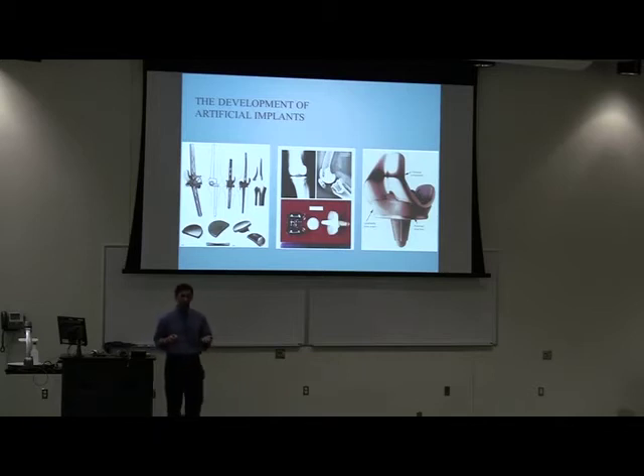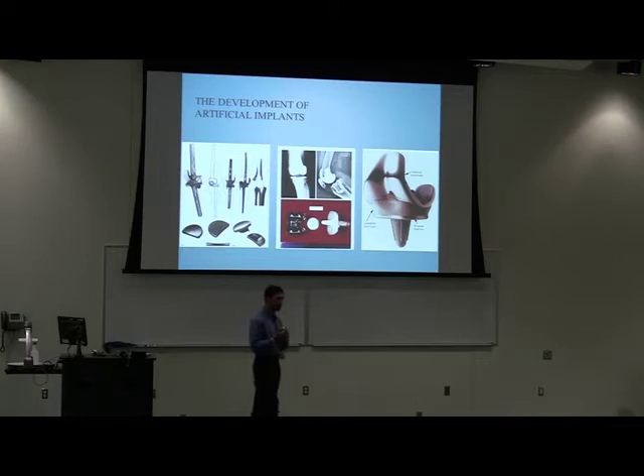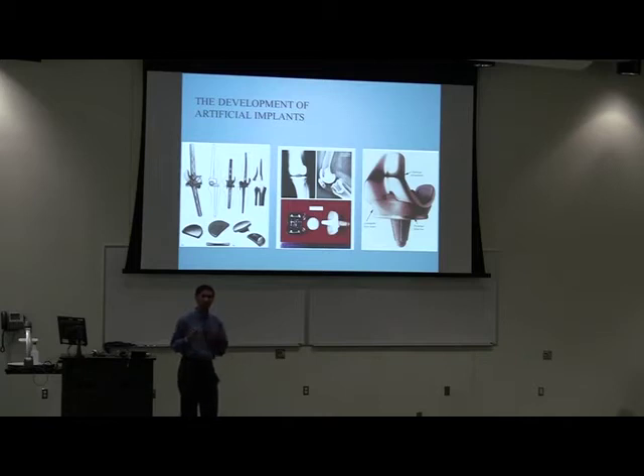One of the first knee or hip implants was done all the way in the late 1950s using Teflon. I'm sure you've heard of the material, like the non-stick coating on your frying pans. That's Teflon. And they chose it because they thought, wow, it's a very slick polymer, very low friction. It should do very well in that joint. But the problem with that was, and it was discovered within the first 1 or 2 years, it wears out at an extremely fast rate.